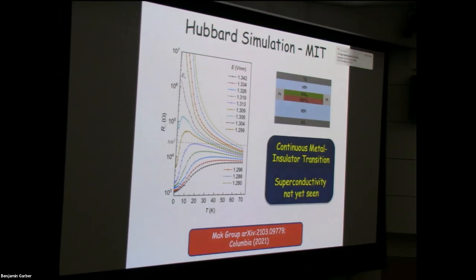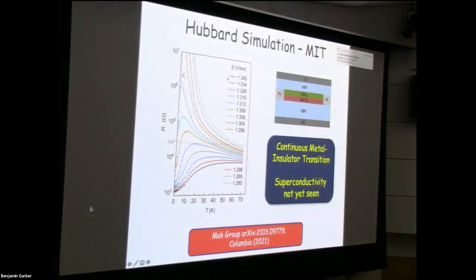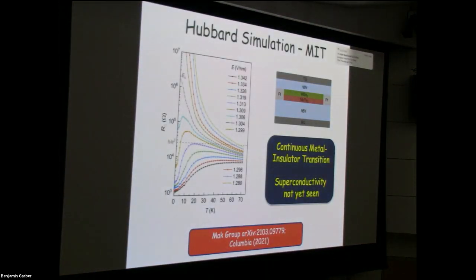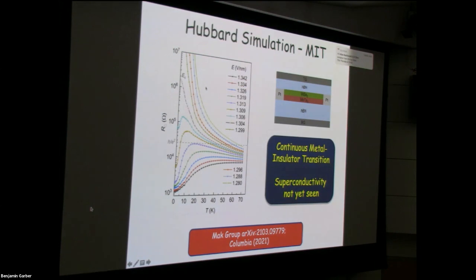This experiment is actually in situ tuning across a metal insulator transition, changing the ratio of the bandwidth to the interaction strength, to go from the band limit in which you clearly have a metal and a Fermi surface and so on, to the insulating limit where the electrons get stuck on lattice bonds. And so this type of phase transition is definitely extremely interesting, and maybe we have a new opportunity to study it experimentally in a new way.